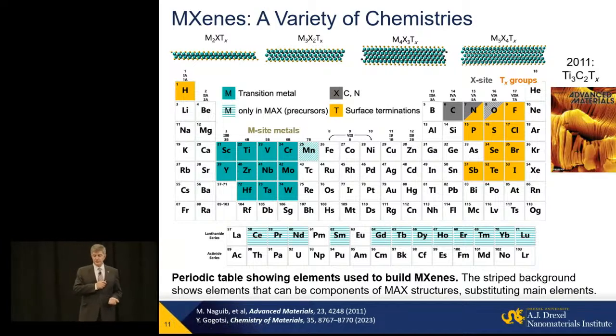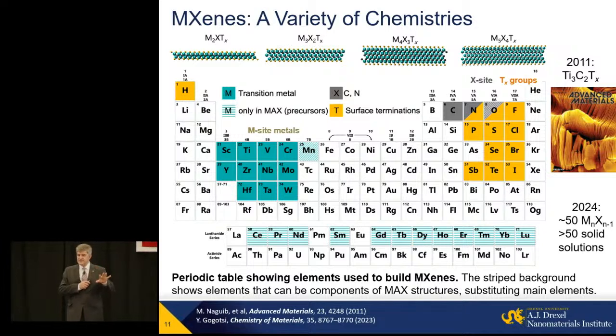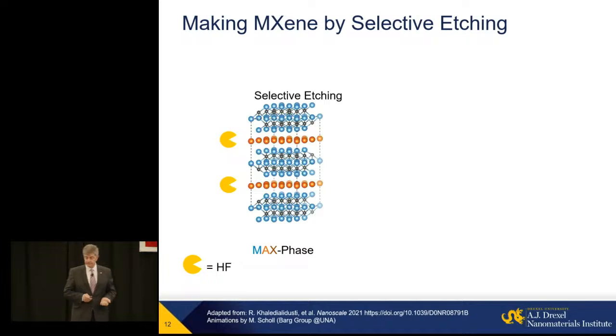When we published the first material, this was titanium carbide Ti3C2 in 2011 with oxygen and OH terminations. More than 50 simple structures have been reported by now, more than 50 solid solutions, and I don't count the surface terminations, which can be oxygen, OH, chlorine, fluorine, bromine, sulfur, and others here. So we get pretty much an infinite number of materials that we're creating in the lab. We're trying to study their properties, and based on properties, develop applications here. And of course, for so many materials, I won't be able to discuss all the properties here.